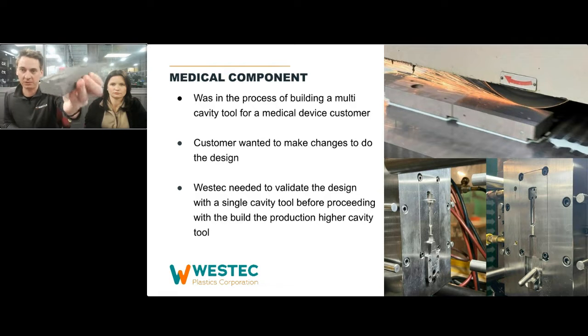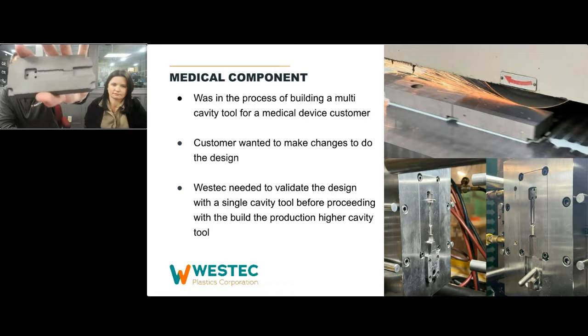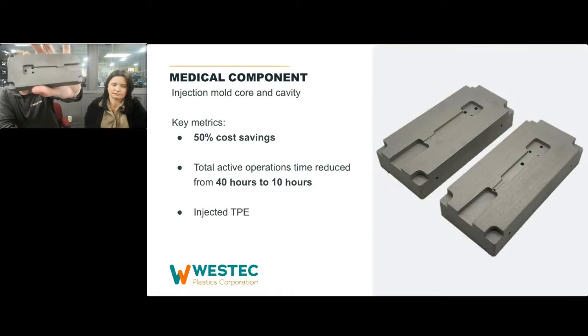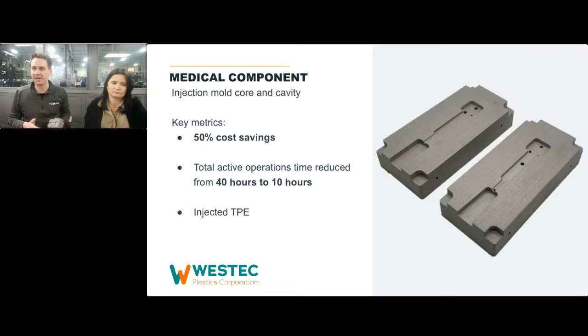It's something that they certainly could build traditionally, but the value here was being able to throw this on the printer within an hour, get it printing over the weekend, over the holiday, and not disrupt their normal shop flow, to be able to print an H13 tool like this. It only needed a little bit of finishing work to get it up and running. So 50% cost savings here. They estimated this would take about 40 hours to build traditionally, but with Mantle there were only 10 hours of finishing work, which for them was a huge advantage, to not have their toolmakers spend 40 hours being disrupted on something like this, but only spend 10 hours after printing.